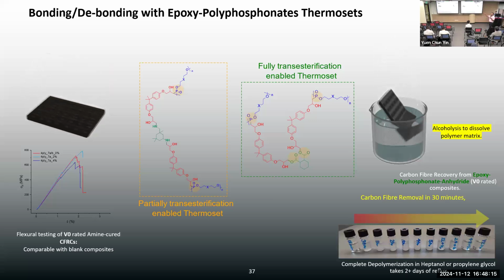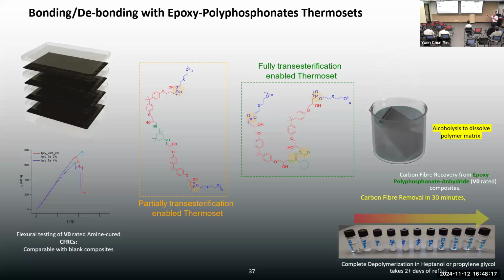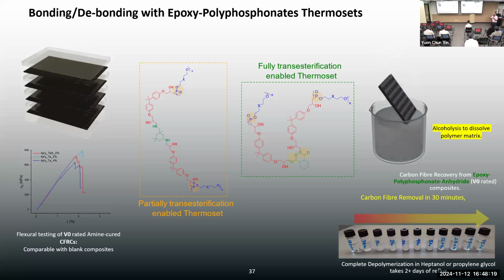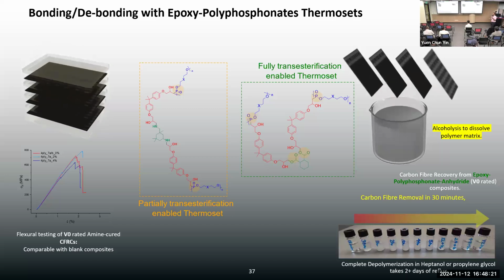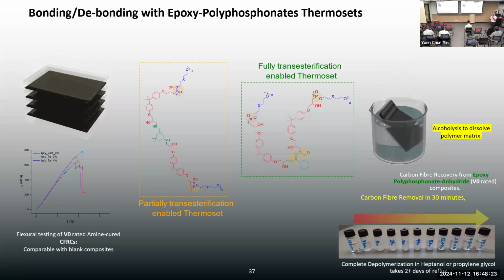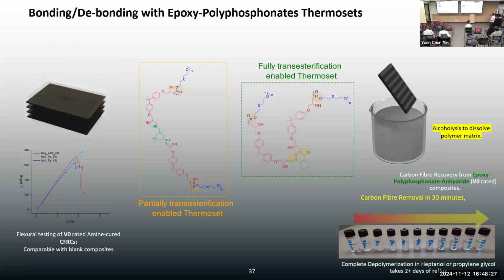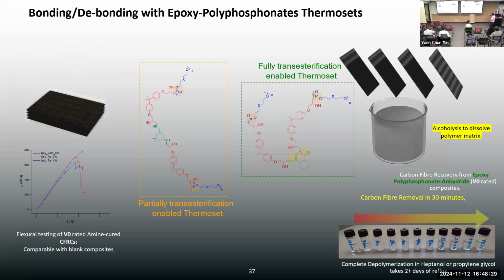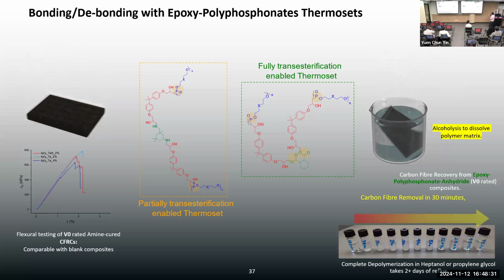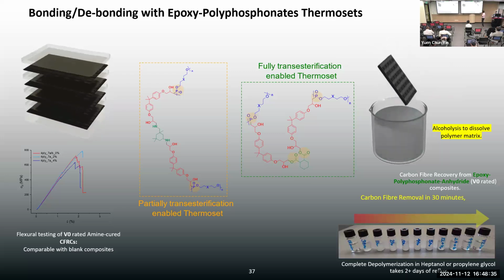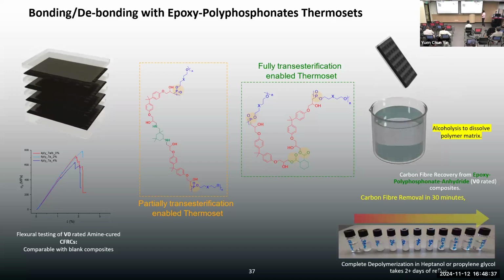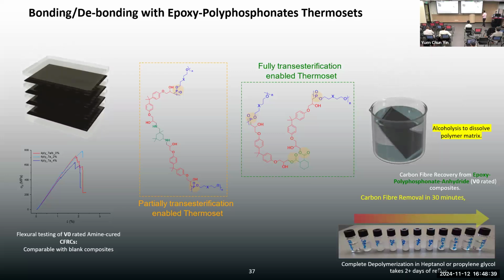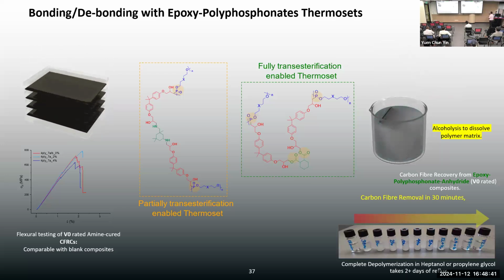In the previous case, I showed you the thermal recycling process, where you just heat back and forth, but then you downgrade the material. In chemical recycling, you need more energy, you need a little bit more chemical, but you can, I would say, recover your fibers fully and also the polymer at one point. You can see in our case, you can just heat up and dissolve the polymer quite easily in alcohol and recover it.